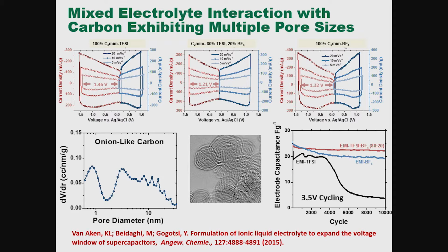But the bottom line is that real supercapacitor electrode surfaces show a range of pore sizes, and this is a film onion-like carbon electrode surface showing the distribution of pore diameter. So you have really small pores, bigger pores here, and big pores there.